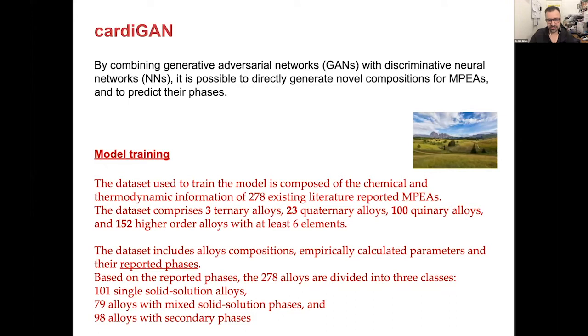Now, the reason why we used a generative adversarial network, I'm going to go quick because I know that time is running out, is that, separately to other machine learning models that are based on a lot of data and data science, there's actually a very small number of existing alloys reported in the literature. We found only 278, which is perhaps even more than you would think. So there's 101 single phase solid solution alloys, some mixed phase, and then some other ones with secondary phases as well. That's not enough for creating a machine learning model.